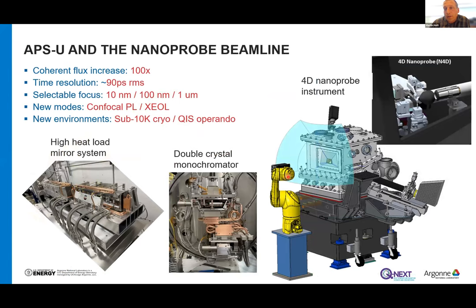And so, yeah, this lets us very flexibly interrogate a lot of scattering space. Then you can actually walk through your momentum transfer using continuous rotation here, as well as small amounts of tip tilt. So you basically have those options. But the main advance is really being able to get both the fluorescence microscopy and the optical spectroscopy out of the same scattering volume, because distributing dose is going to be key in not killing the sample, and being able to do that deterministically is very important.